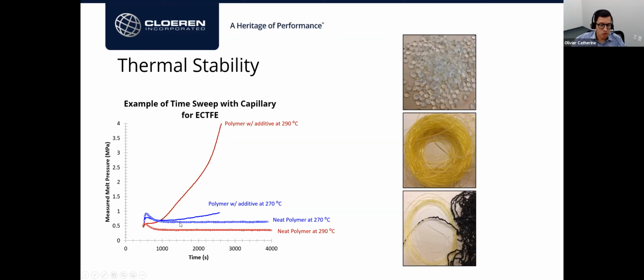You can see cross-linking doing a similar trend, but sometimes we also see degradation where the material molecular weight is going down and the viscosity is going down as a result. So for example, if you are looking at PET and you have a little bit of moisture, over time you will see a decrease in viscosity. So it depends. In this particular case, I did not know the chemistry of the additives.